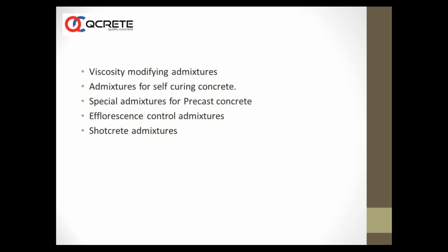Then we have admixtures to help the self-compacting concrete makers. As self-compacting concrete came into the market, we have another problem where when we use a PC based admixture to make self-compacting concrete, many times bleeding happens, segregation happens. To counter this, we have viscosity modifying admixtures. Some are based on xanthan gum and similar materials, added at very low dosages, like 0.01% by weight of cement, which hold the concrete together in a viscous state.